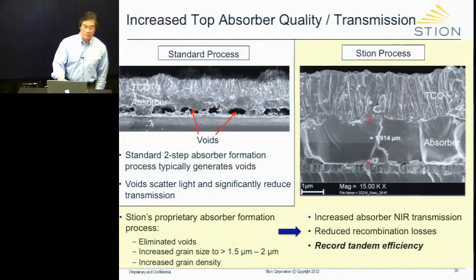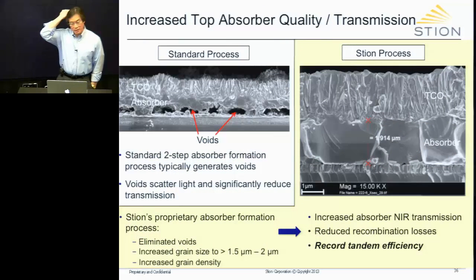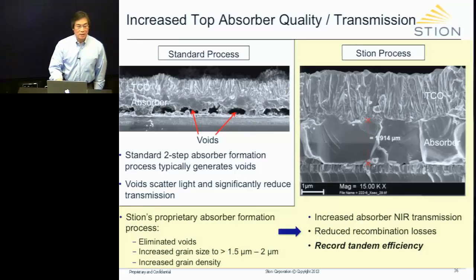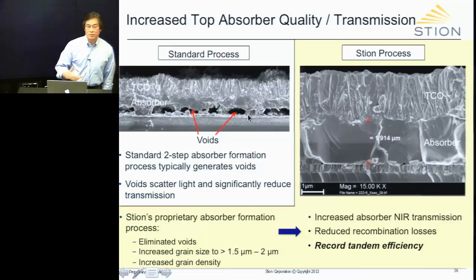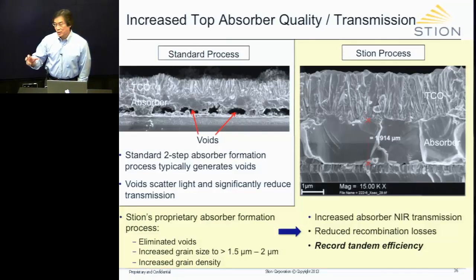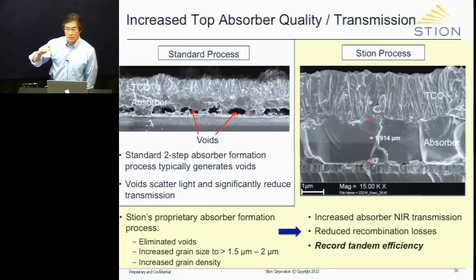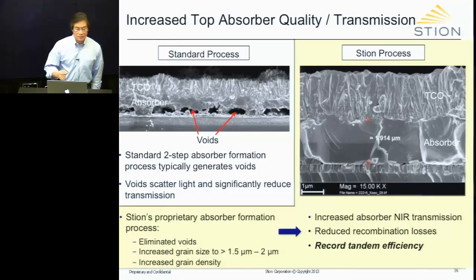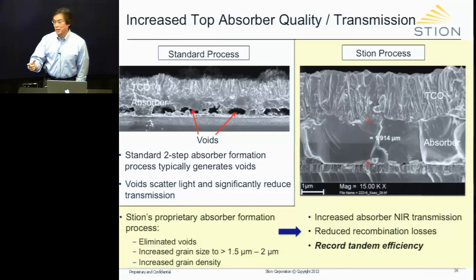So here's the net result. This is the top absorber, and I'm going to spend a little time explaining what's happening here. In the standard two-step process I just described to you, the absorber looks like this. Notice that there are a lot of voids there. Keep in mind how we did this, right? We deposited thin film metal precursors, and then we reactively annealed it, which means that the reaction surface is on the top of the precursor layer. So in order to have that reaction occur, there has to be mass transport from the bottom to the top. That, in part, explains why there are voids there, because you have to move material from the bottom to the top where the reaction occurs. The second reason is that going from metal to semiconductor, there's a lattice expansion on the order of 2 to 3. And so that's another problem as well.